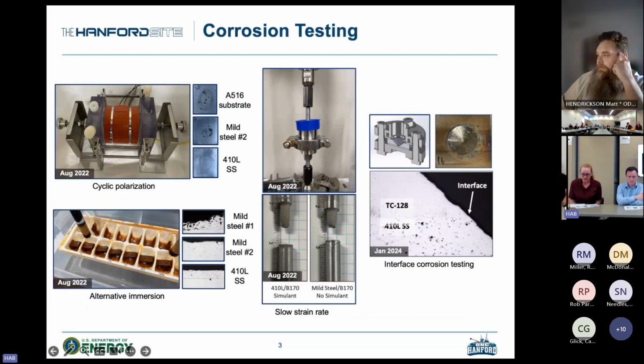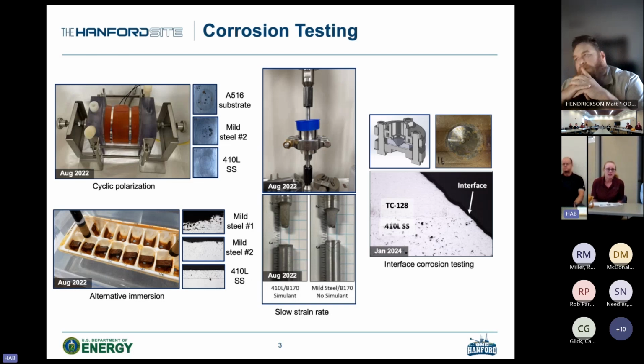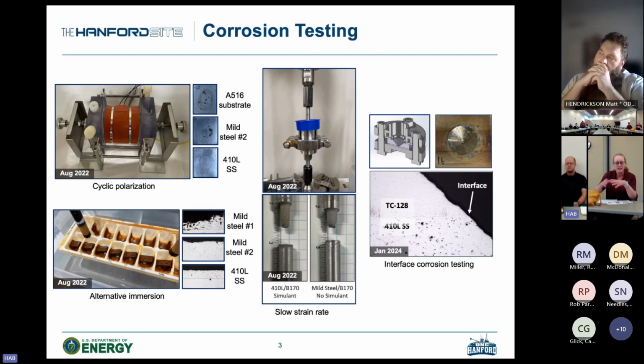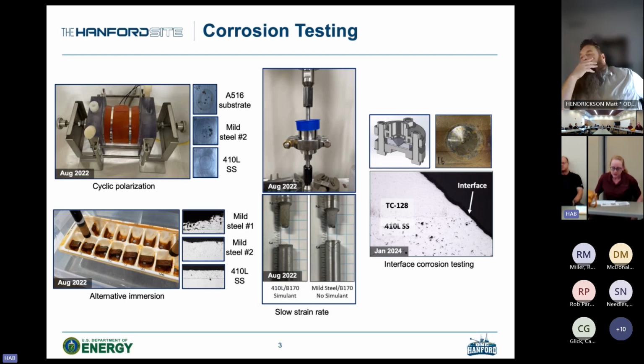So if you look on the right-hand side, there's a black and white image. What you're seeing there, I have denoted TC 128, that is our mild steel, which is representing our tank liner material. And then you have 410L stainless steel. You can see a division where those two materials meet, and in the 410L stainless steel, you see black dots. Those black dots are voids or part of our peening material, which is a ceramic blasting bead. So you can see the porosity of these samples.